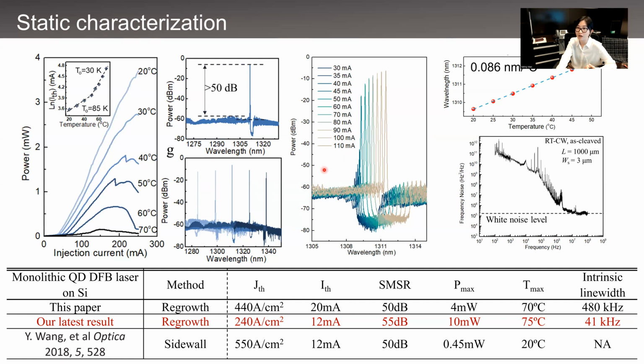And with an increase in temperature, the mode slightly shifts at a rate of 0.086 nanometer per degree Celsius without mode hopping. And the intrinsic linewidth of the device was measured to be 480 kilohertz, and in our latest round, this value was reduced to 10 times smaller. So compared to the state-of-the-art results from other groups, the monolithic quantum dot DFB laser presented here has better performance in terms of threshold, power, and temperature stability. And most importantly, an intrinsic linewidth of tens of kilohertz is pretty low compared to typical solitary quantum well laser linewidth, which is several megahertz.